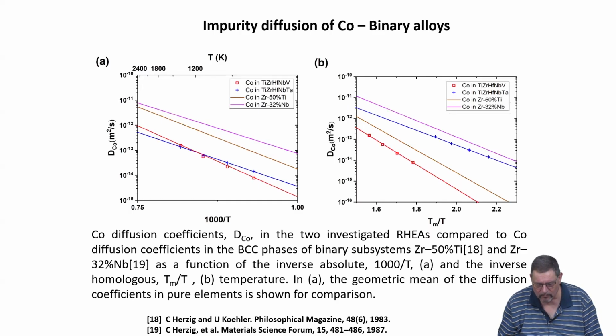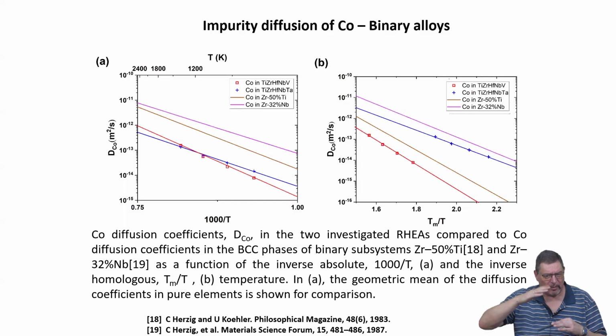And again, looking for a comparison between two refractory high entropy metals and BCC phases of these subsystems of the high entropy system, we have kind of the same acceleration, deceleration type, because going from absolute temperature to homologous temperature just changes for these systems a lot. So it means, again, we are here in the same situation almost, but a little bit more strongly concerning the numerical values which we see as compared to the Cantor high entropy system.